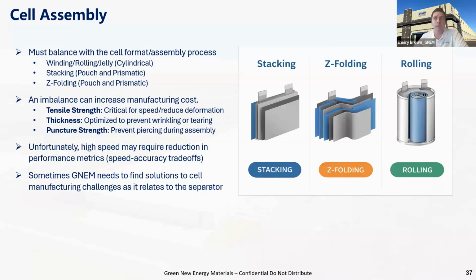And I can't overstate this enough, because unfortunately, when you go high speed, high volume, sometimes there's got to be a slight reduction in the performance metrics. It's very difficult to go to high volume manufacturing, put a sub-10 micron separator in that, and not expect to see wrinkles, rips, and tears occasionally. This is a really big problem for cell manufacturers. We call this the speed-accuracy trade-off. This is one of the major challenges where our technical team works with manufacturers to help bring separator designs that meet their manufacturing challenges. It's one of the big challenges in separator manufacturing.